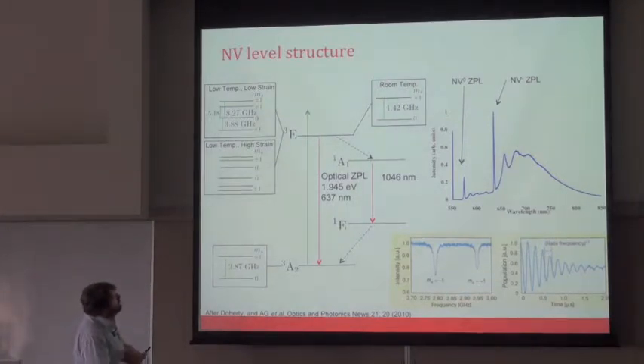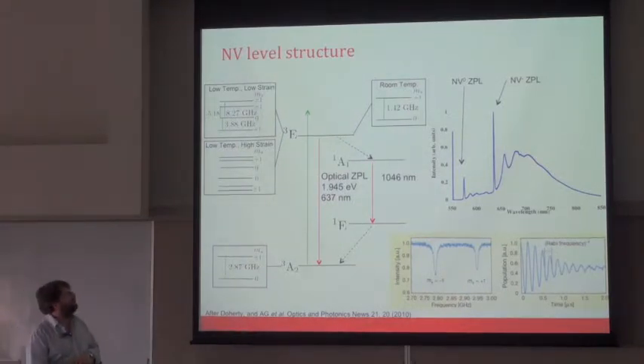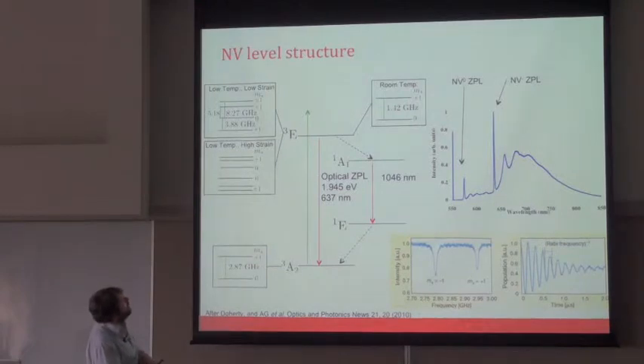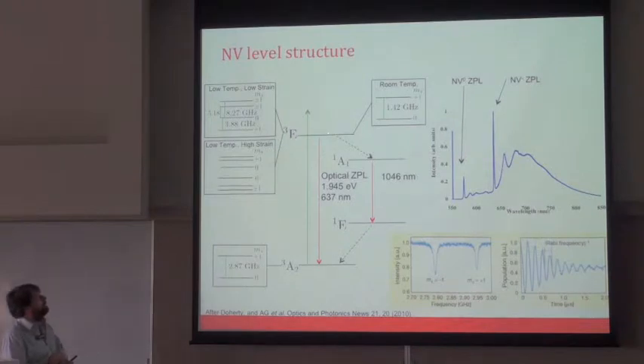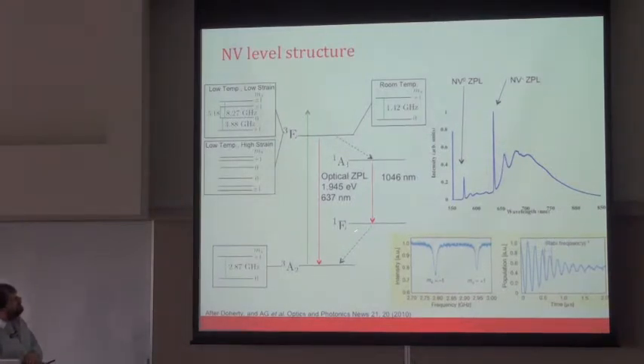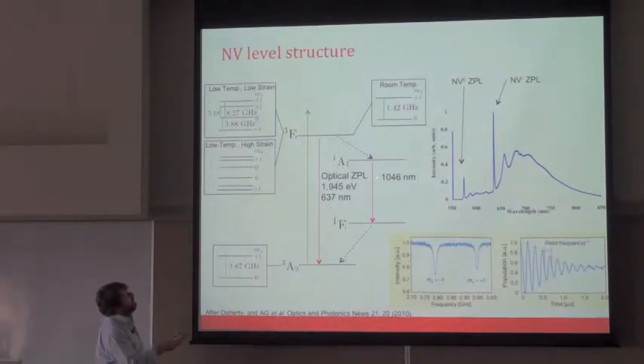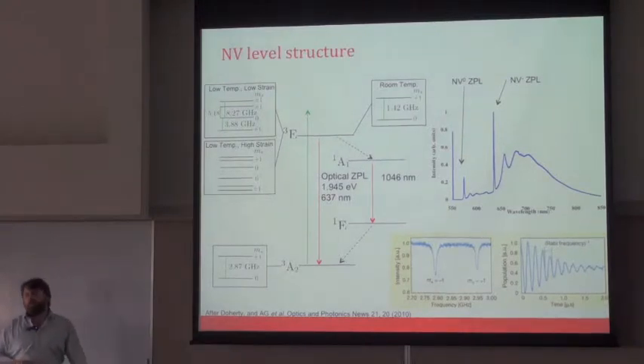This emission here makes the NV center a bright single photon source, and if that's all it did, it would be quite interesting. But the magic, for want of a better term, that's gotten people really excited is this side transition here, the singlet transition. And so every so often, if you are in the plus or minus one state, you can decay from this excited state manifold into the singlet pathway, emitting a photon in the near infrared, and then coming back to the spin zero ground state.